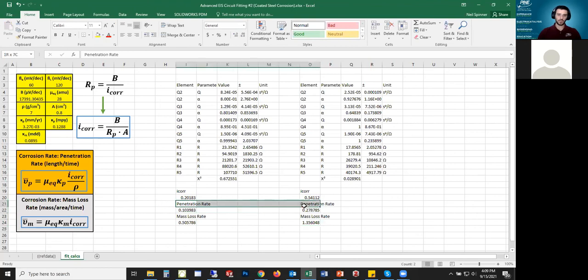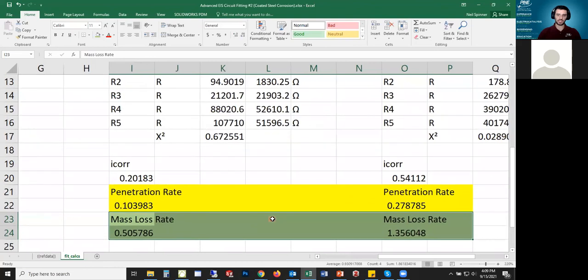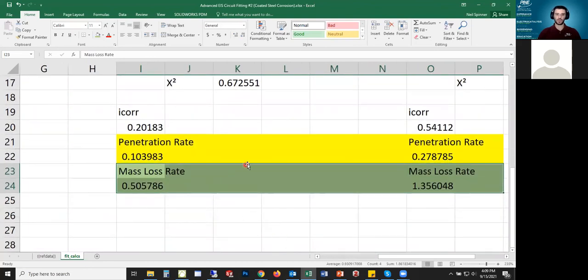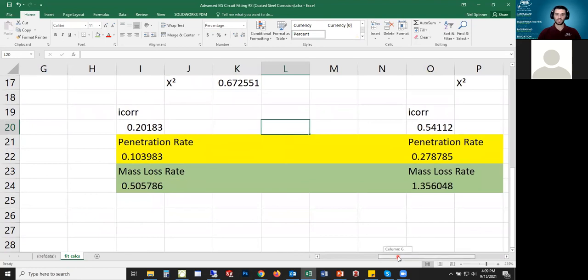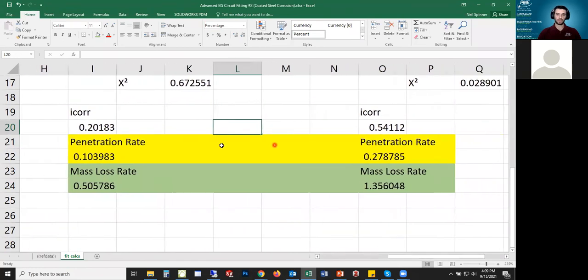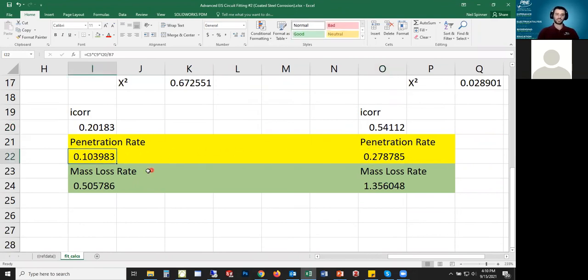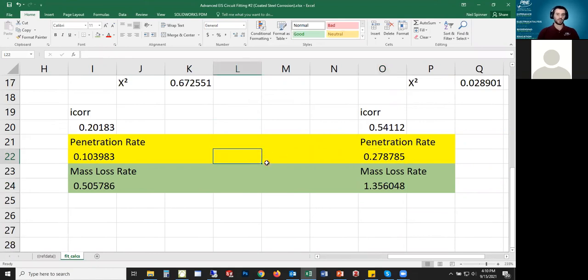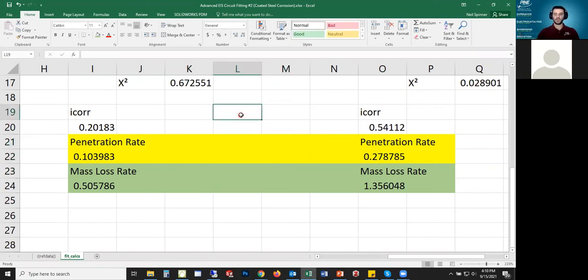And so now I'm just going to illustrate these values here and say that I've assumed some things. This is a researcher's data, this is not my data. But essentially, numerically, what I can show you is that 24 hours versus 360 hours, I would expect the corrosion rate to be higher after more time has gone by. And that's what I'm seeing here. Penetration rate and mass loss rate goes up by about a factor of three, two and a half to three times greater corrosion rate after more time has gone by. And that intuitively makes sense. This is an example of a potential numerical quantitative analysis of this kind of data.